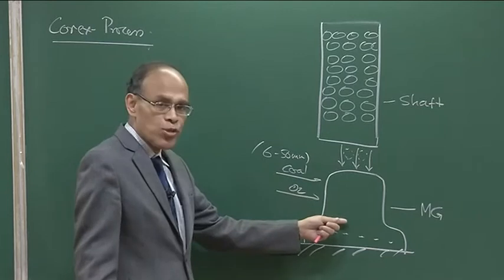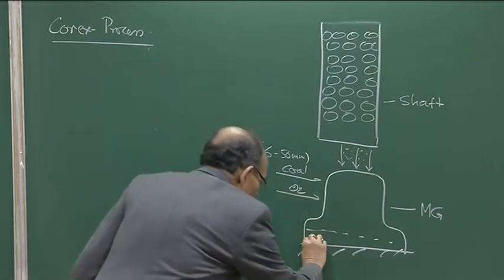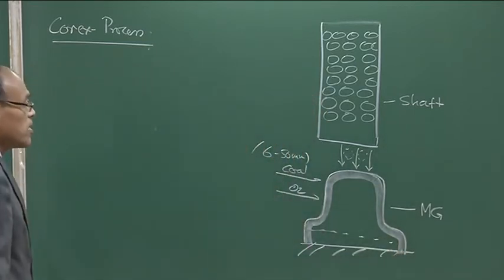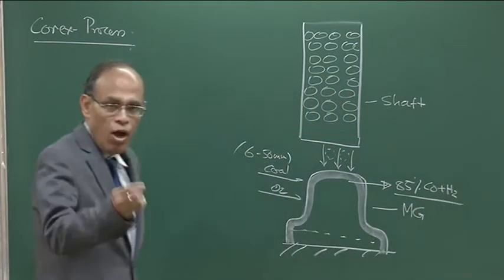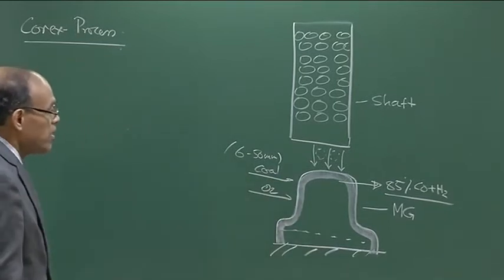This pre-reduced mass enters the melter gasifier, along with coal and fine particles of 6 to 50 mm size, possibly mixed with some coke as well. There is pure oxygen and intense agitation, which promotes all kinds of chemical reactions. It is a high-temperature, intensely reducing environment within the melter gasifier.